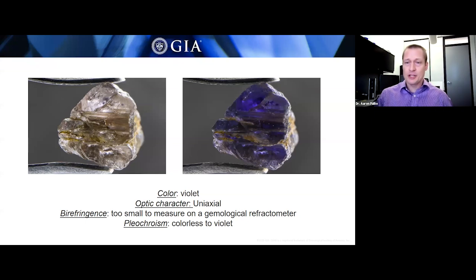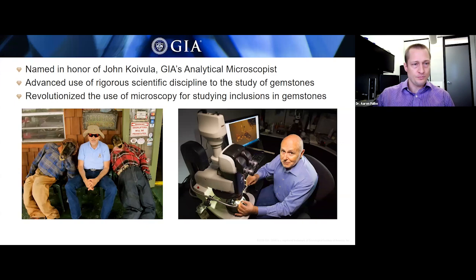But despite this very small birefringence, it does have very different optical properties in terms of the way it absorbs light in different directions. What you're seeing here in these two photos is koivulaite in the microscope with a polarizing filter, and the polarizing filter has been rotated 90 degrees between these two directions. You can see the color goes from almost colorless in one polarization direction to this very deep, rich, vivid violet color in the other direction. And so I thought that was very unique, and that's one of the defining characteristics of this new mineral.